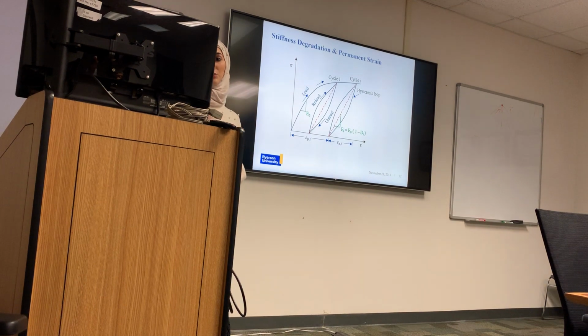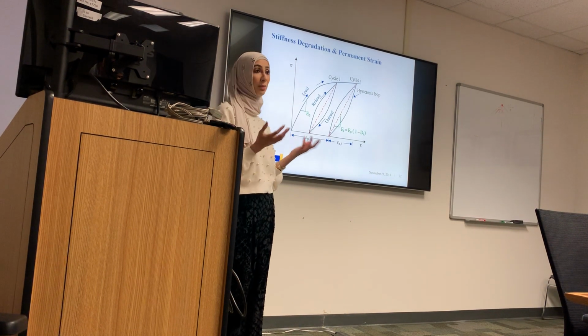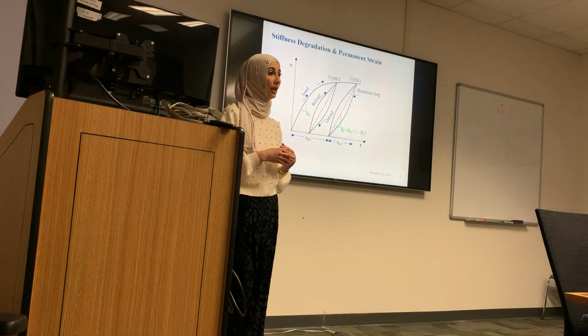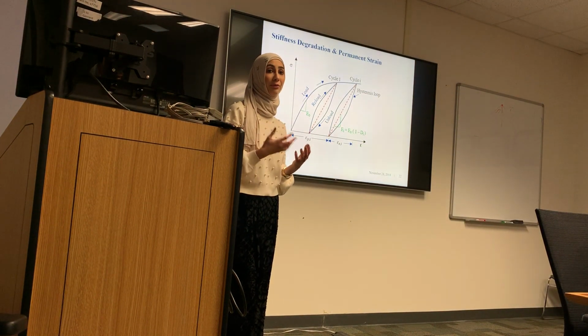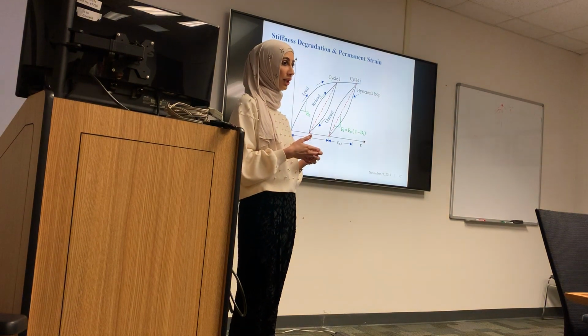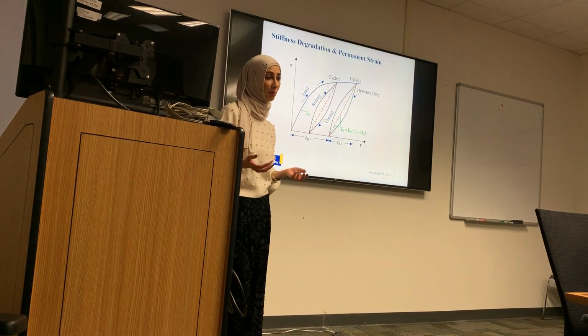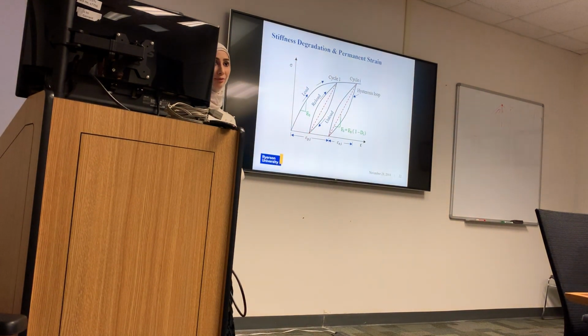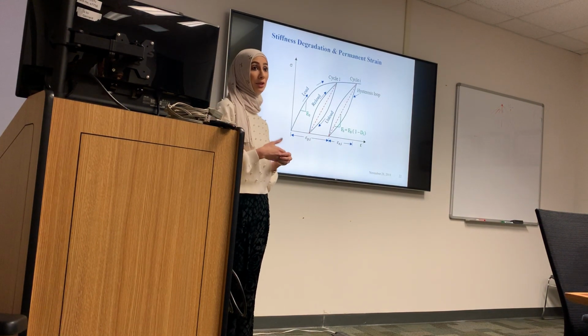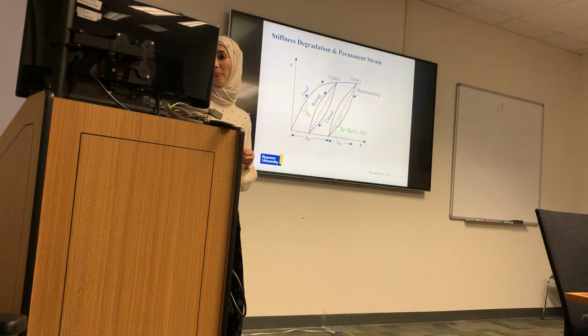Each cyclic load, we measure the deterioration in the modulus. We know when the composite or any material experience load and unload, they tend to have different damage mechanisms such as delamination, interfacial failure, interlaminar failure, and those are permanent strain which cause actually a deterioration in the modulus.